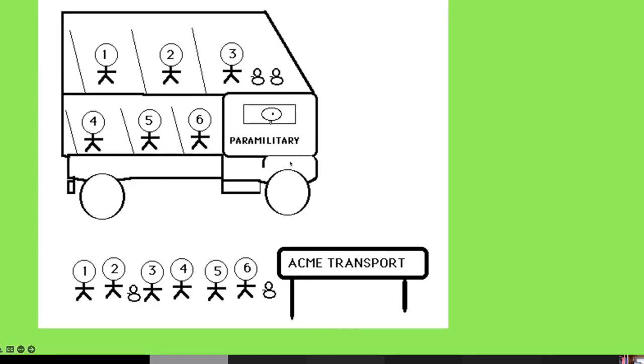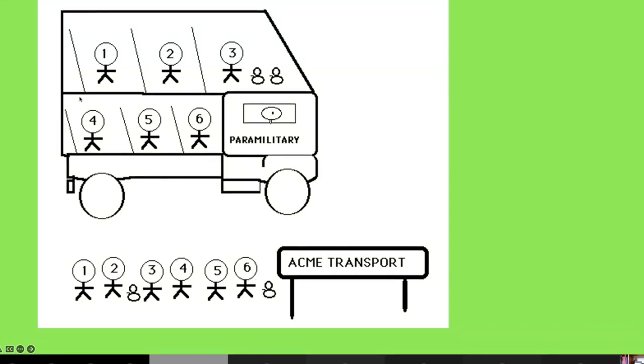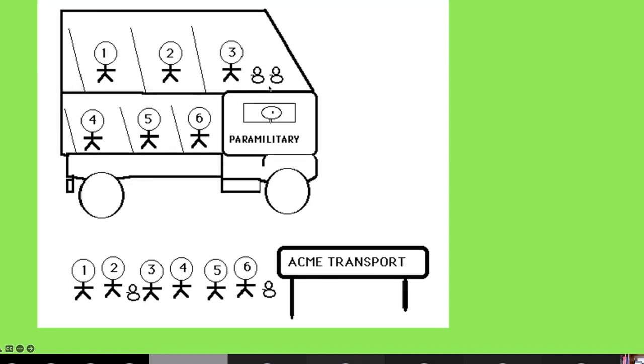This is what we call paramilitary, where we have small atoms here who, when the bus comes along, just rush onto the bus, ignoring the sequence in the queue, whereas the large atoms move in a disciplined manner. So we have an atomic correspondence as far as the large atoms are concerned, but the carbon reaches a location where it has the lowest free energy. So it diffuses during a paramilitary transformation, but the large atoms do not.